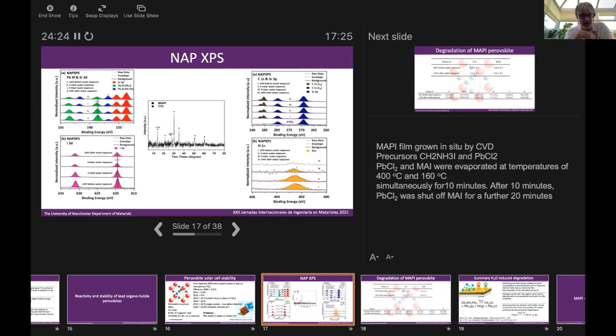Then we turned off the lead chloride and we kept the methyl ammonium iodide going for about another 20 minutes or so. We then took the sample into the chamber and we annealed it, or heated it, to about 100 degrees centigrade just to get full conversion of the material to the perovskite that we wanted. So here's the XPS spectra that we got from these measurements.